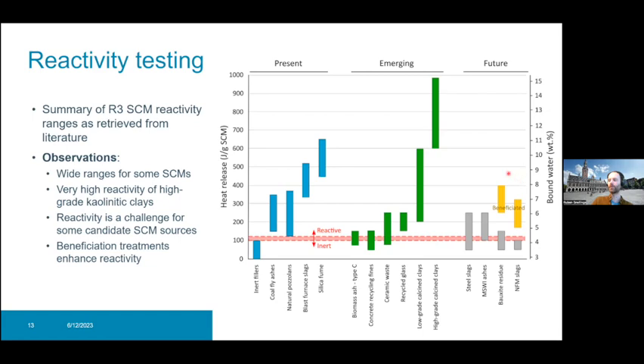What's also shown here is that if you do some beneficiation, and we'll talk about this a bit later, for instance for non-ferrous metallurgy slags, you can transform an initially inert material into something which has reactivity and contributes also to performance.